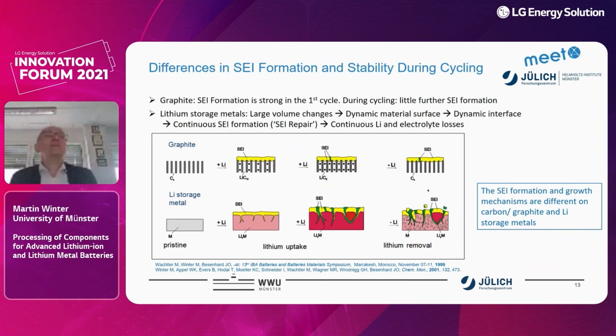What we also know is that these materials, for example, the lithium storage metal like silicon, have a different SEI formation, but also SEI cycling behavior. Unlike graphite, where the SEI basically forms in the first cycle, lithium storage metals show very large volume changes and have a dynamic material surface. This gives a dynamic interface to the electrolyte, and we have continuous SEI formation, so-called SEI repair. And this leads to continuous electrolyte losses and also continuous lithium losses. And in a lithium-ion configuration with limited lithium ions available, this is basically the death programmed inside a lithium-ion battery. So lithium consumption leads to capacity fade, and capacity fade leads to limited cycle life. These pictures have been created around 2000 and are frequently used by others in newer versions of this picture.